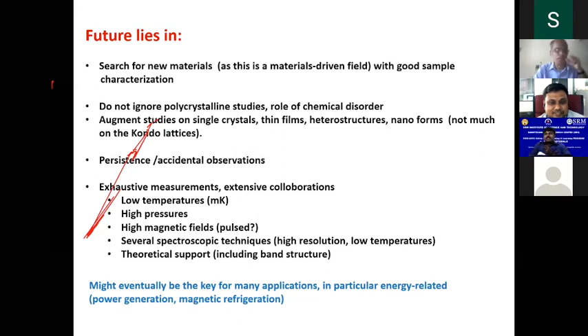Okay. I have one question. So when this 4f electron becomes delocalized, what happens to the anisotropy? Very good question. The point is that all these materials have been studied on single crystals. You see anisotropic behavior, anisotropic hybridization, since the 4f orbital has crystal field effects. At high temperature you have a fully degenerate orbital; at low temperature under crystal field splitting, the crystal field level has its own orbital shape, and depending on direction, the low lying states have different orientations.